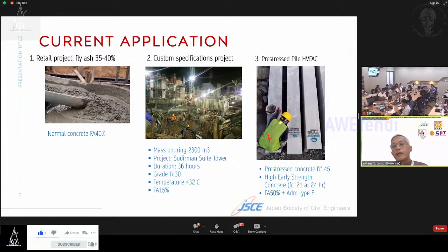In the next application, now we have produced pre-stress piles that use high volume fly ash concrete. So the pre-stress concrete grade is FC 45 megapascal, and it must be high early strength concrete because we need to release the steel cable within 24 hours.